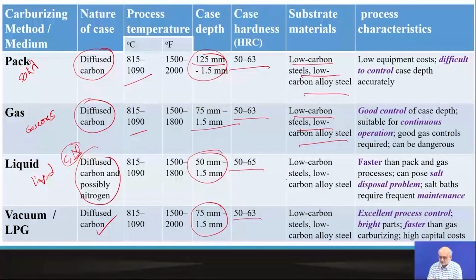But now look at the overall process characteristics. As I said, this is difficult to control because the thermal state is higher than room temperature, and you cannot bring it to room temperature instantly. But this is very low capital investment and is conventional, very easy. You don't require very skilled manpower, so very easy to implement. In case of gas carburizing, you have better control over the case depth, and this is ideal for continuous operation, which is not possible for liquid bath or pack carburizing, which are batch processes.